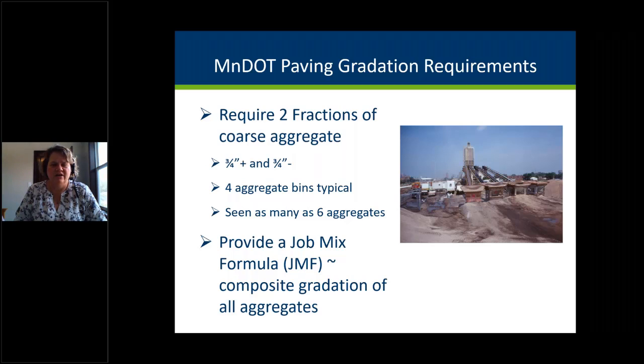At the height of our development and implementation of our specifications, we would typically see 4 aggregate bins. We would see some sort of an intermediate aggregate, pea rock, buckshot, or coarse sand material. We'd see our fine sand. We'd see a 3/4 plus and a 3/4 minus aggregate. And still to this day, the contractors, if they can find an intermediate aggregate that meets quality and fits into their mix, are striving to use that because they see the benefits of the ride from that.